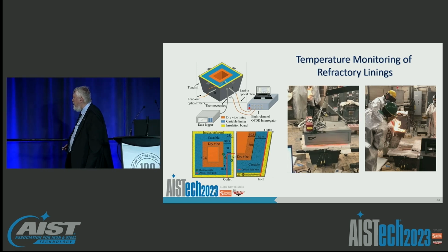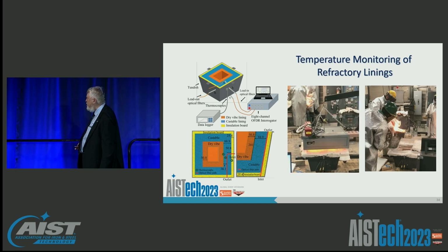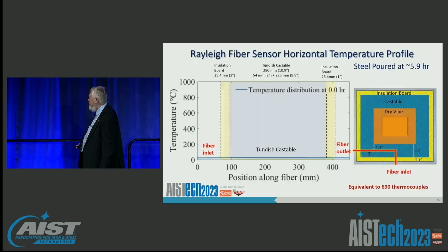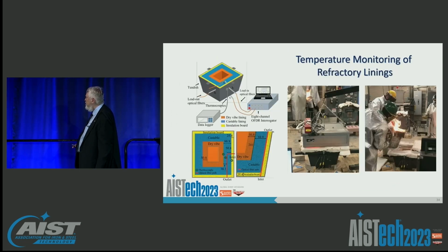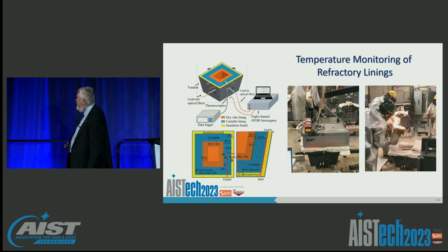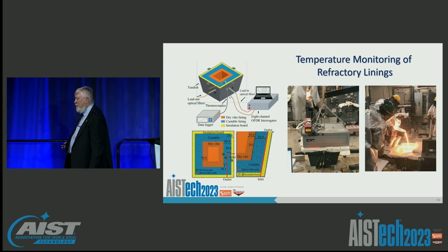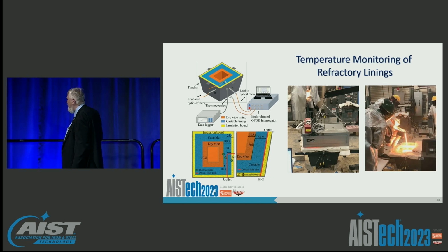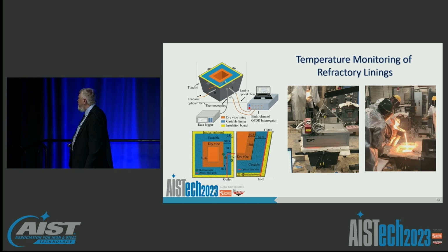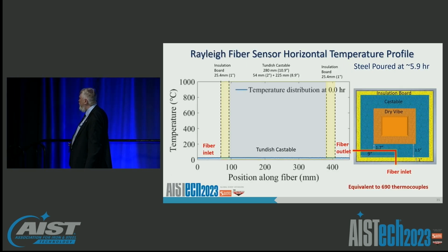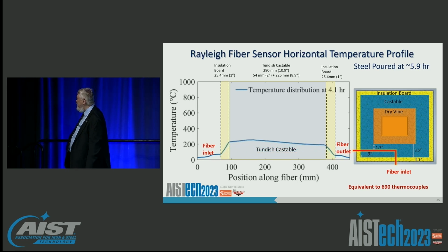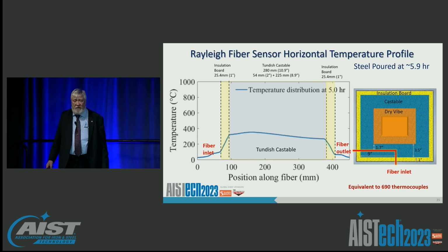This is some of our laboratory experiments in a mock tundish where we've put a fiber in. And I guess I'll show it below. So we actually expose it to an environment simulating essentially a dry vibratable tundish lining system. And then we take that fiber path through the permanent lining, and we can replay the thermal profile going through that permanent lining and passing through the insulating linings. And once again, one fiber giving you a whole profile of information.